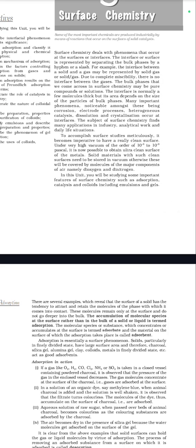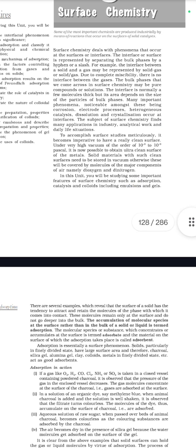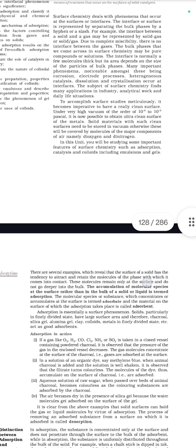To accomplish surface studies meticulously, it becomes imperative to have a really clean surface. Under very high vacuum, of the order of 10 raised to the power minus 8 to 10 raised to the power minus 9 Pascal, it is now possible to obtain ultra clean surfaces of metals. Solid metals with such clean surfaces need to be stored in a vacuum, otherwise these will be covered by molecules of the major components of air, namely dioxygen and dinitrogen.